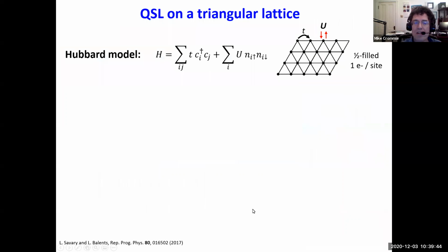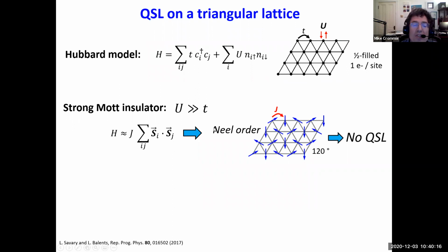To think about where it might come from, a nice place to start is the Hubbard model. Let's consider this triangular lattice and fill it with electrons so it's half filled, 1 electron per site. Then we can describe the behavior of the electrons with the Hubbard model. I have t, the hopping parameter that tells me how the electrons hop from site to site, which gives a bandwidth. I have U, the Coulomb repulsion between 2 electrons on the same site. Now, if U is really huge, a lot bigger than t, then this complicated Hubbard Hamiltonian reduces to the simpler Heisenberg Hamiltonian that I show down here. The ground state for this Hamiltonian is the 120-degree Néel order, and that is not a quantum spin liquid.